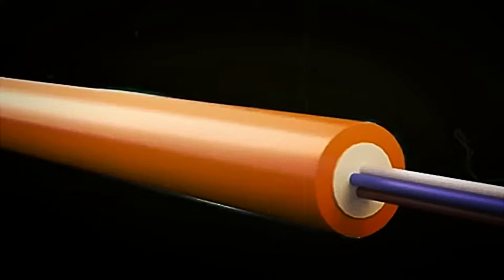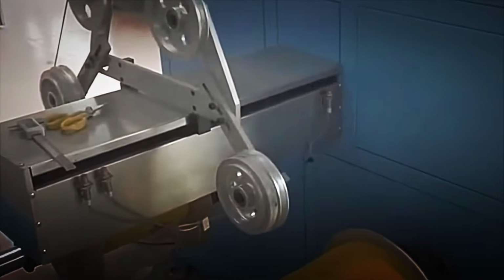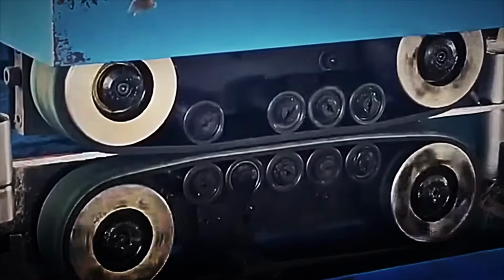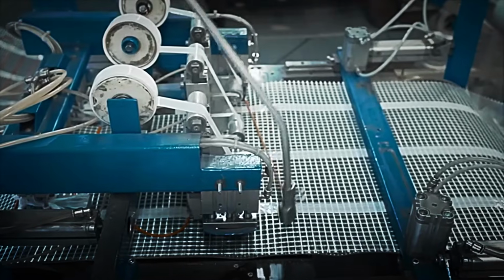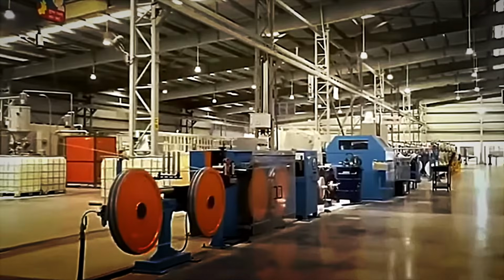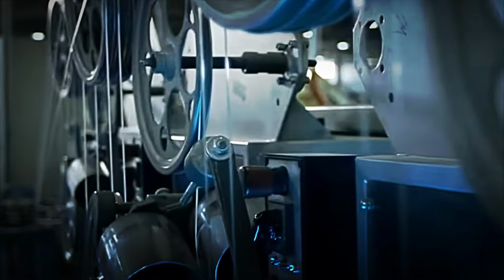To solidify the polymer, the fiber passes through curing chambers with high-power ultraviolet light. Upon irradiation, the material polymerizes instantly, hardening without slowing down the production line. During the coating process, optical systems verify the thickness of each layer. If any layer exceeds or falls short of the programmed value, the machine adjusts the polymer pressure or the intensity of the UV lamps. The end result is a fiber coated with micrometer precision, flexible, strong, and ready for handling in the subsequent manufacturing stages.